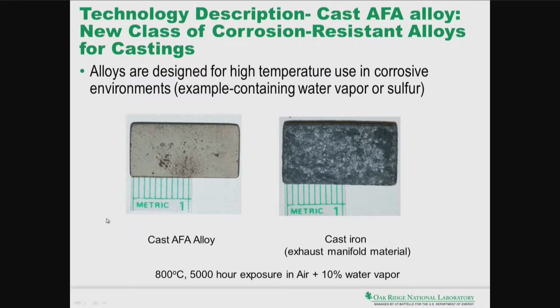So let me just start with a brief description of the technology. What we're talking about is a new class of corrosion-resistant alloys, and these alloys are designed for high temperature use in corrosive environments. On the left, I show here a piece of cast alumina-forming alloy that has been exposed to a temperature of 800 C for 5,000 hours in an air plus 10% water vapor environment. On the right-hand side is a cast iron subject to the same conditions, and you can see the difference in the surface quality after the exposure. So clearly these alloys are able to resist the environment containing water vapor and or sulfur.